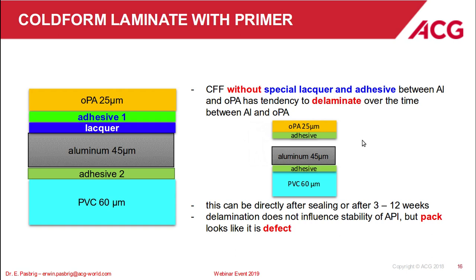If someone is selling you a cold form laminate with primer on the outer side, you should ask whether it's tested first, and second, whether the adhesive and the lacquer are compatible. On the inner side, the adhesive is the same as for the material without primer, which you see on the right-hand side. From the point of view of protection, both materials are the same. There's no difference for the protection of the product. The difference is only related to delamination resistance. Material without primer will delaminate after 3 to 12 weeks under accelerated stability conditions. You cannot avoid this. It can be reduced if the sealing temperature is a little bit lower or if the cavity is not very stiff, meaning bigger than normal, but you cannot avoid delamination.